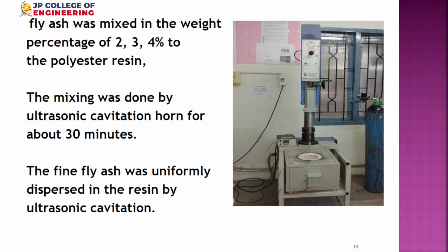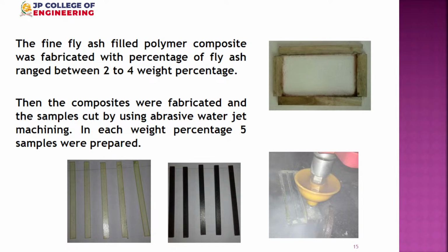Next slide, please. This is done in an almost liquid state, a viscous liquid like castor oil or honey. It will be like a honey condition, where you put the particle and then stir them together. Normally if you get sick, your mom used to take honey, put pepper powder, mix them and give it to you. The same way we put the resin, put the fly ash particle, but for mixing we use ultrasonic vibrations.